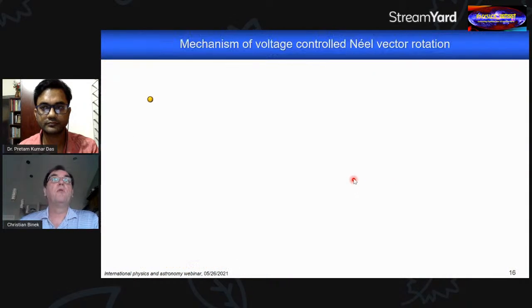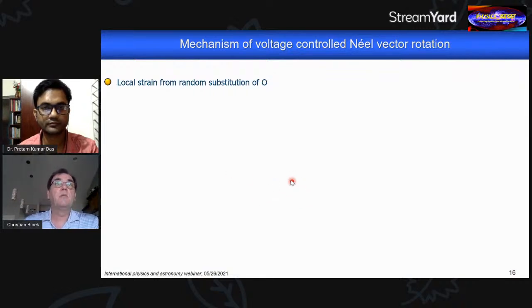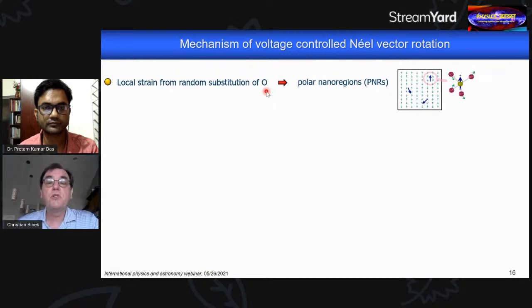Okay, so now a few more words about this mechanism, which I sketched already a little bit. So we think what happens is the following. The substitution of the oxygen by boron creates these local polar nanoregions. And now if we apply an electric field, all these polar nanoregions are oriented in the same direction, giving rise to a macroscopic polarization of the system. And with the macroscopic polarization comes a uniform and macroscopic piezoelectric effect, a global straining response, which is in proportion to the applied electric field and mediated by this piezoelectric coefficient d_zz. Now this straining, in turn, gives rise to a coupling. There's magnetoelastic coupling.